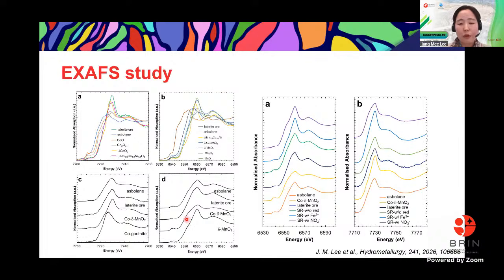But in the case of cobalt, it's really challenging to check the EXAFS range, because cobalt is a really tiny amount in the laterite ore system, and there is interference from the iron signal, which is in really large abundance in the laterite ore. But I will do a synchrotron study using a spectrometer which can specifically eliminate the iron signal, and then we can get a really accurate cobalt signal from the X-ray absorption spectroscopy. So if you want to do some collaboration in this way, let me know, and I will be able to check the cobalt K-edge EXAFS signals through that.